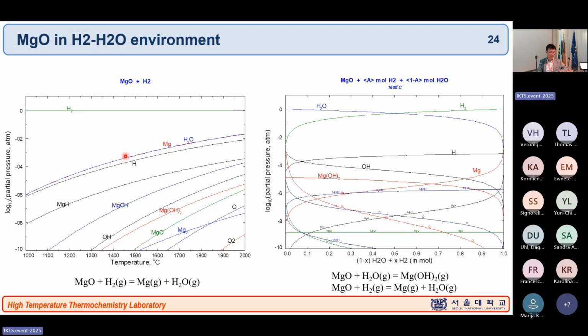But you can see that the magnesium partial pressure and H2O partial pressure are picking up very quickly with increasing temperature. Theoretically, if you see about 10 to the minus 4 partial pressure, it means it's enough to see actual degradation already. So at about 1300, 1400 degrees, if you put the magnesium oxide under hydrogen condition, you can start to see some magnesium vapor forming. That's what is really happening.